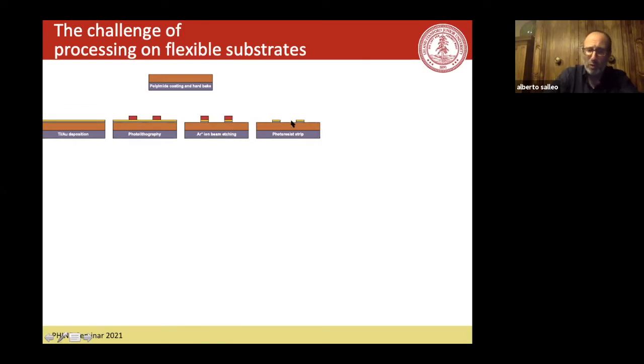And that's just a metal. Now, then we have to put the polymer. And actually the challenging part in reality is the polymer, because it seems trivial to adapt a process that's used for silicon to polymers, but these polymers actually get completely destroyed by the chemicals that are used in the silicon process. So we have to come up with a process that uses the same chemicals, but doesn't damage the polymer. Otherwise, this is not going to be really scalable. But even this very first step actually turned out to be quite challenging.